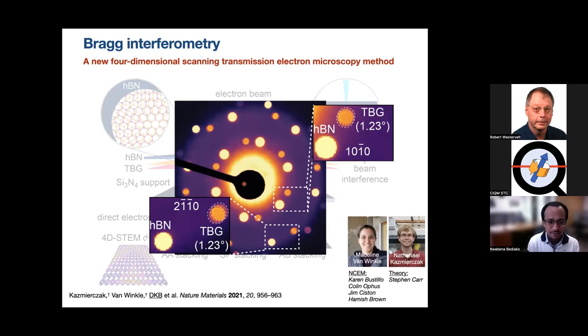Traditional 4D STEM strain mapping, where we would basically map or analyze the centroids of our diffraction disks. They are disks because the beam is converging, and so on our diffraction plane, we get disks, not points. So what we set out to do was to map the deformation of the reciprocal lattice as we move from one point to another. That was a problem because of the very types of samples we were studying.